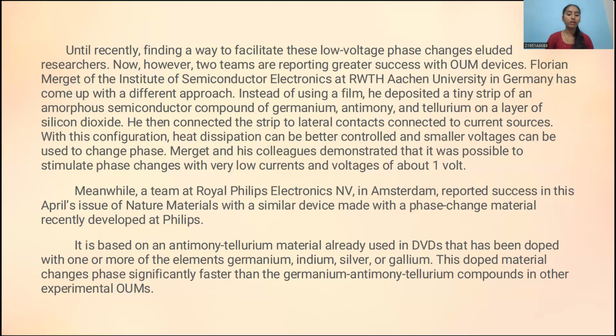Meanwhile, a team at Royal Philips Electronics NV in Amsterdam reported success in this April's issue of Nature Materials with a similar device made with a phase change material recently developed at Philips. It is based on an antimony tellurium material already used in DVDs that has been doped with one or more of the elements germanium, indium, silver, or gallium. This doped material changes phases significantly faster than the germanium, antimony, tellurium compounds in other experimental OUMs.